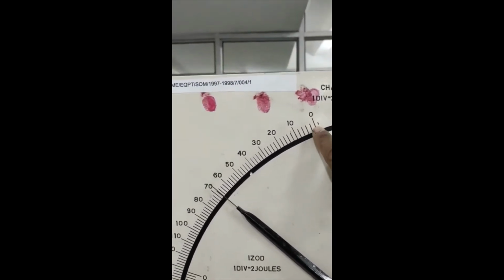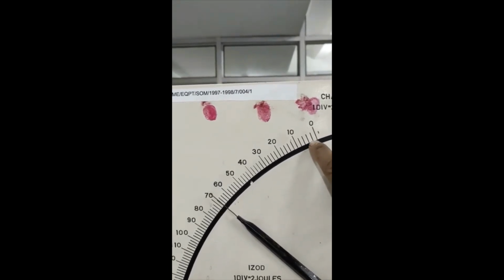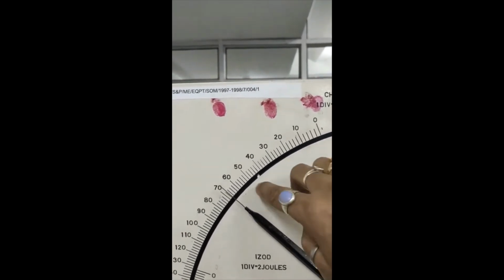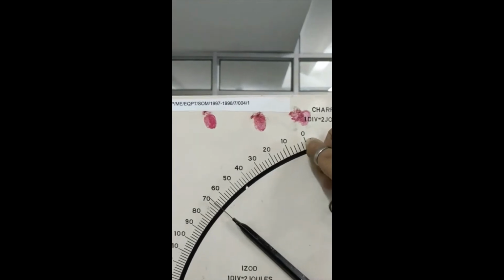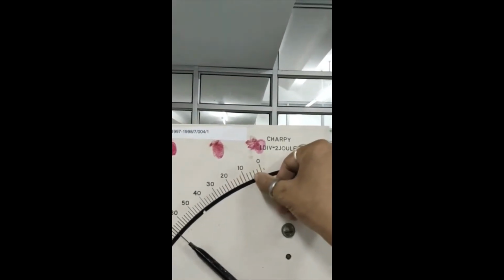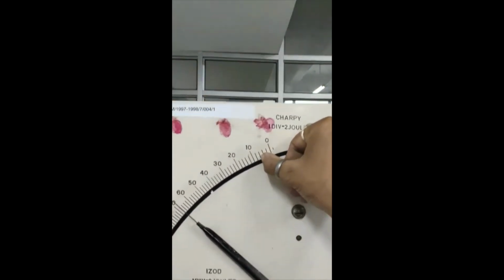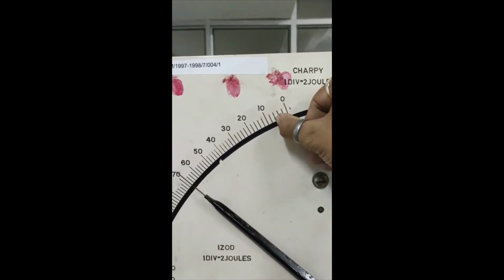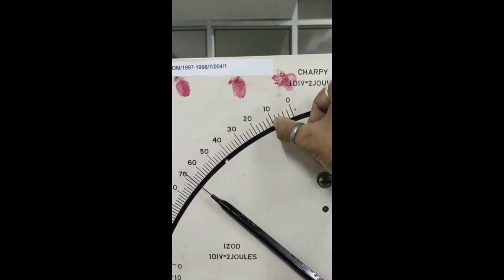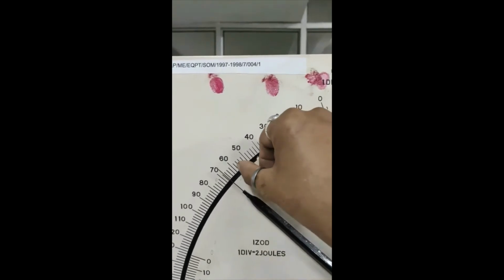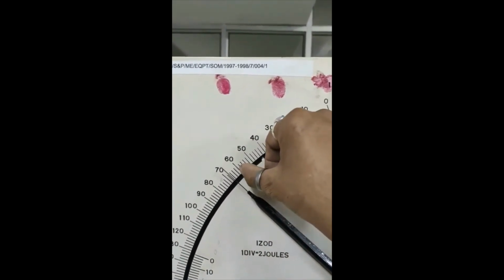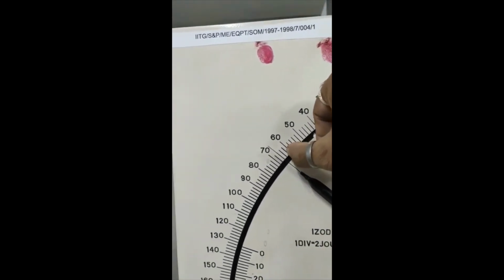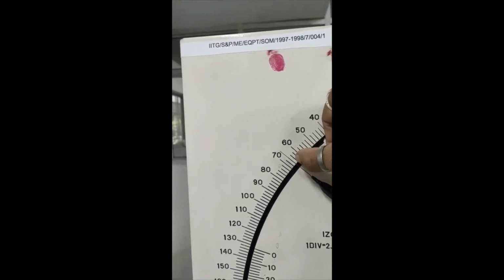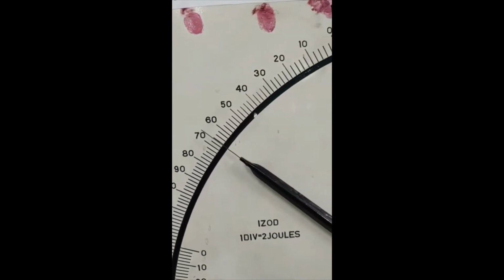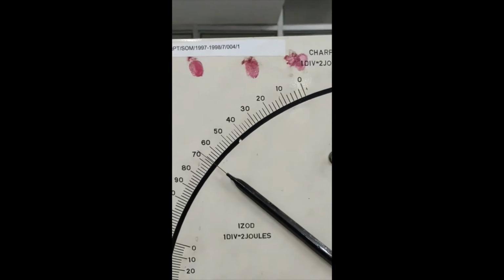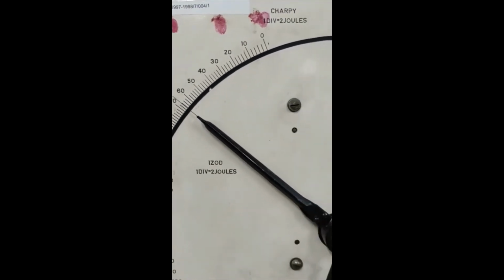You count from 0: 1 division equals 2 joules. This is 2 joules, 1 division is 2 joules. 4, 6, 8, 10 joules. This one is 10 joules. And here you can read directly. This is 60 joules. 62, 64, 66 joules. Almost 66 joules of energy was absorbed by this material.